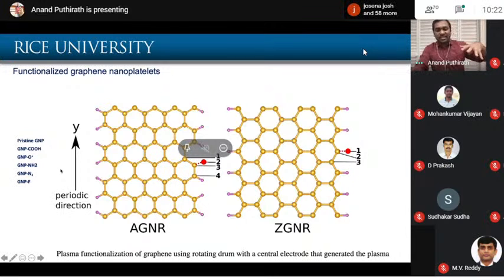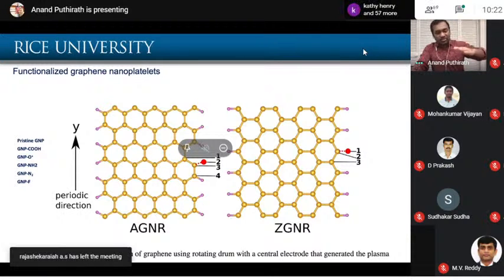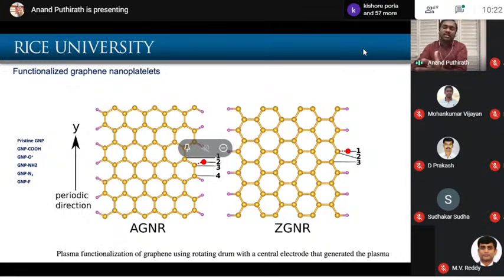So what we tried is a systematic way of functionalizing the system and seeing which functionalization is detrimental, and which functionalization can improve this property. Or if you have capacitance, which is charge storage, what you call the electrocatalytic capacitance, we don't want to attach the hydrogen atom to the system, but it should come to the surface and it should release as soon as the charge transfer happens. So these are two different things, and we are just wondering whether these two things are complementary or not, and the results were really interesting.